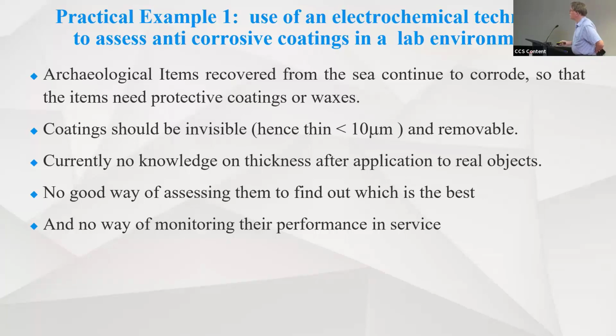Now, this first part is using DC resistance, which is acceptable in lab tests, short-term lab tests, like we were doing, a couple of measurements of a volt applied for a few seconds. But out in a real situation you don't necessarily want to apply a big voltage on a real item. So we use electrochemical noise in the second part.